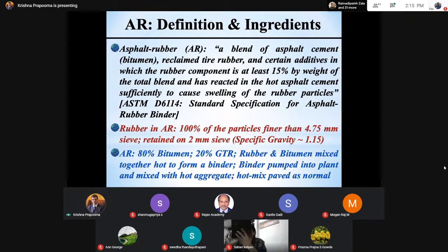So there is a beautiful interlocking effect. All of the interstices, or what we call the voids, the porosity, those get filled with the smaller particles, which is why it becomes a strong material. It's dense. Now, if you talk about the gap graded, you have too much amount of fines. So a few proportions of sieve sizes in the middle portion get eliminated. So it becomes a gap graded. And one example of gap graded, if you are very familiar, is the SMA, stone mastic asphalt. That is also gap graded. It's a cousin of our gap graded structure.